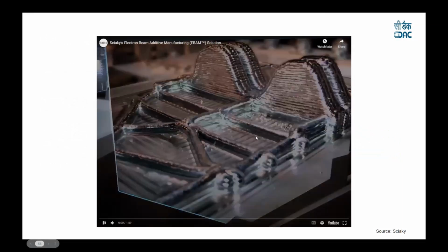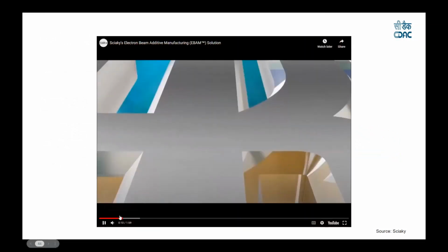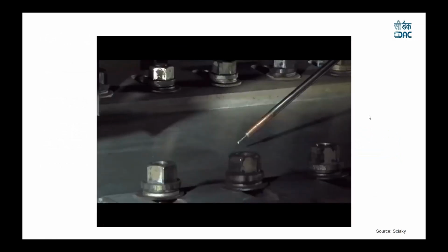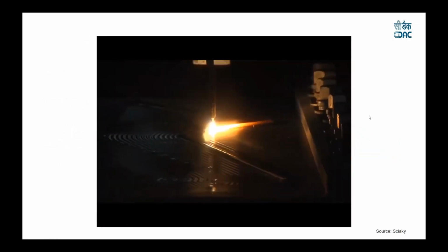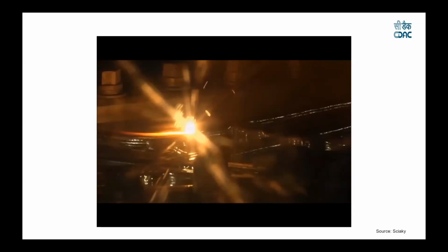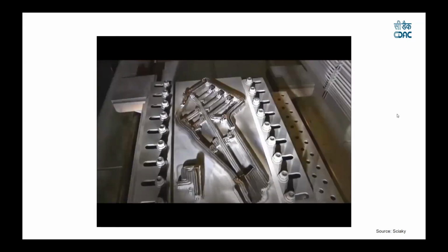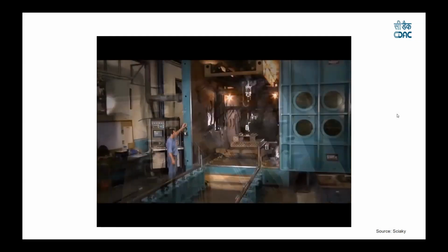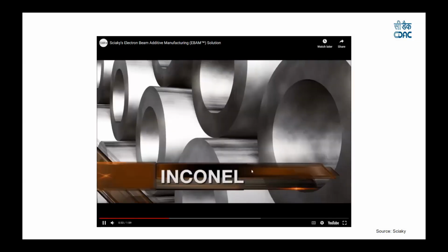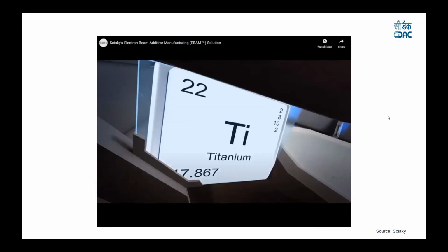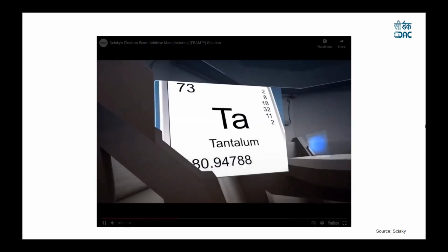So you can see the video, but the surface roughness is very bad. Electron beam additive manufacturing, or EBAM for short, is Sciaky's exclusive process. Metal 3D printing is not limited by part size, material, or geometry. You can manufacture parts and structures that exceed 19 feet in length, 4 feet wide, 4 feet high, and 8 feet in diameter, so it has a virtually huge build area. It can build any metal, including Inconel, stainless steels, and refractory alloys like titanium and tantalum.